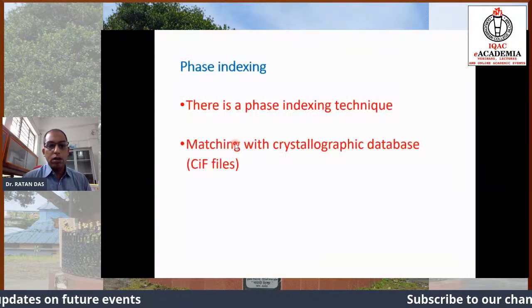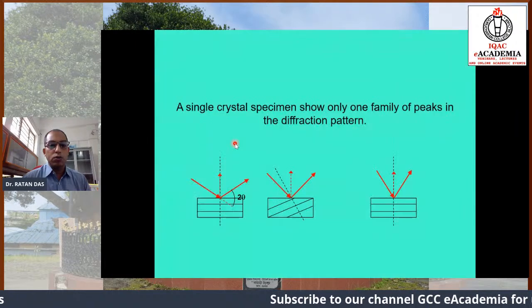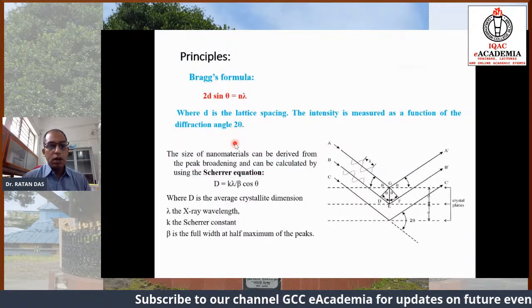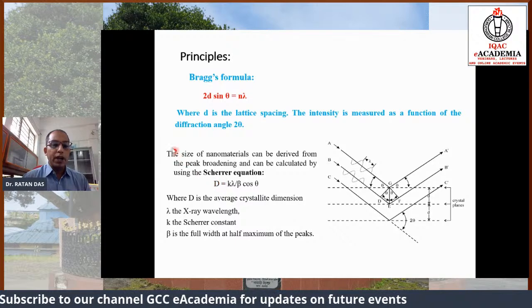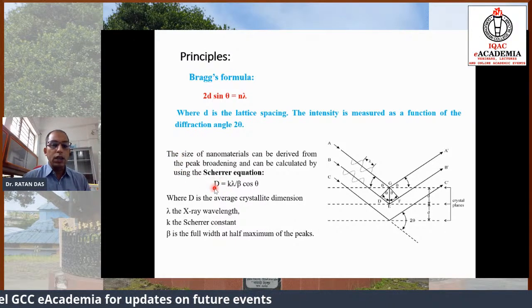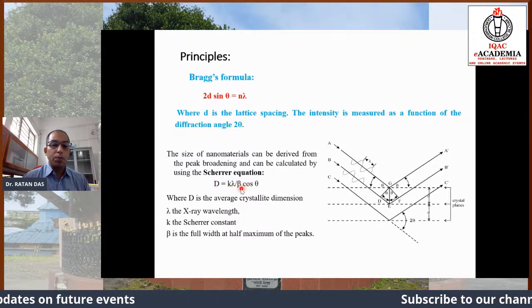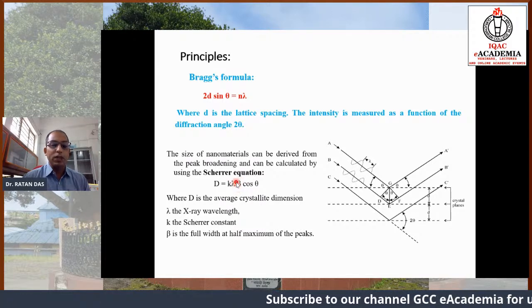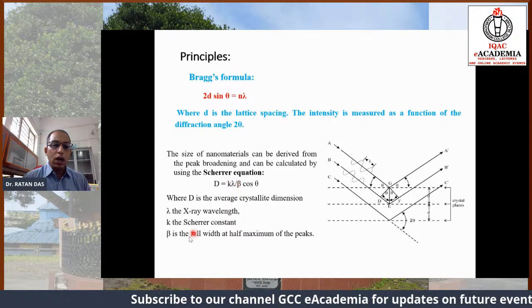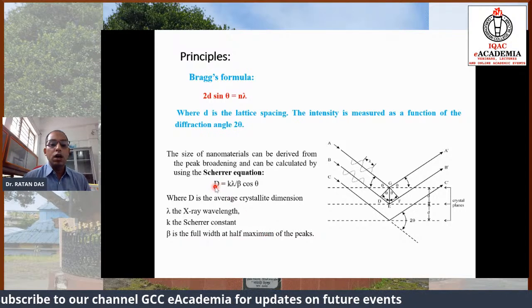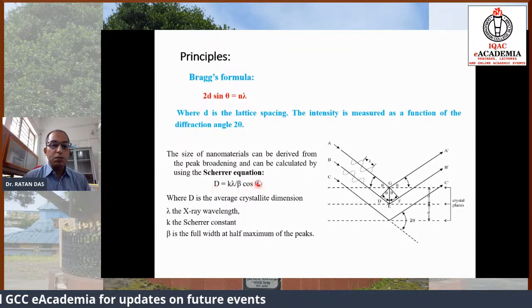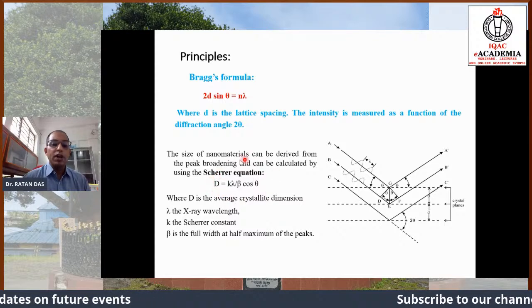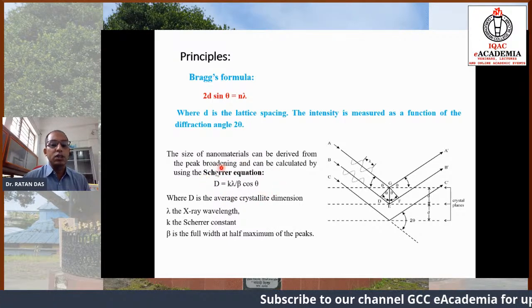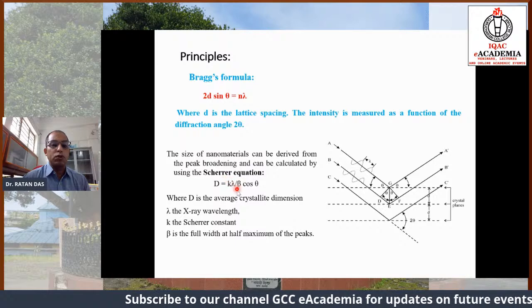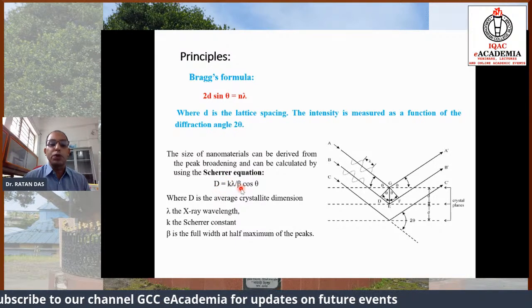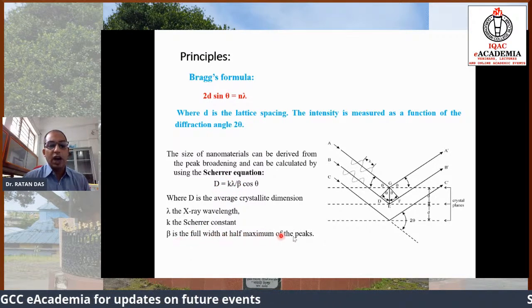And going back to the slide, I want to show you the formula that Scherrer obtained: D is equal to K lambda divided by beta cos theta, where beta is our full width at half maxima. So the higher the width, the smaller is the size. Okay, this is very important. That's why I told you beforehand about this particular Scherrer formula, because D is inversely proportional to beta. Beta is our full width at half maxima.